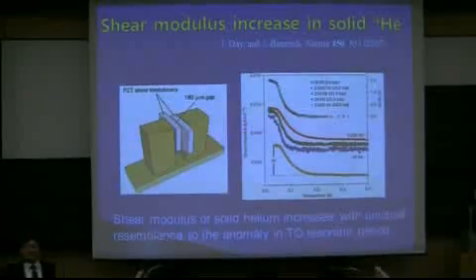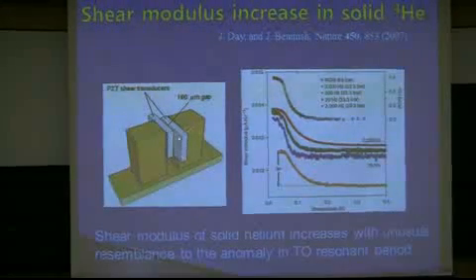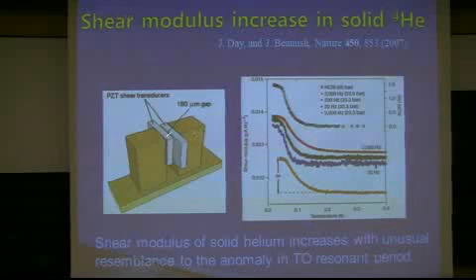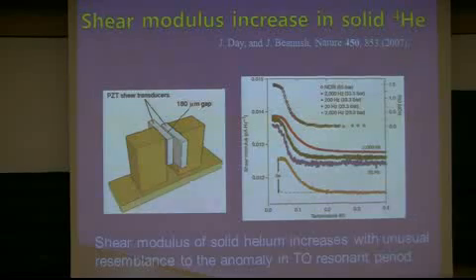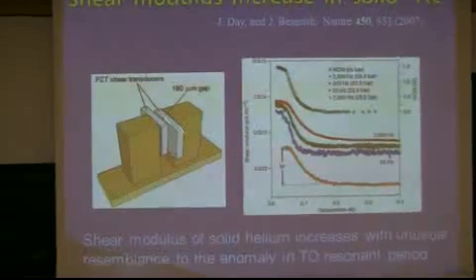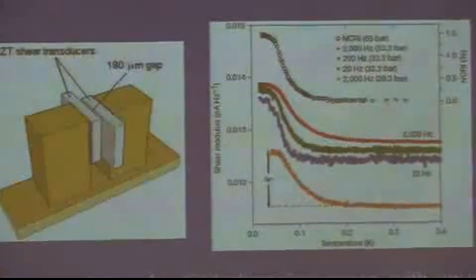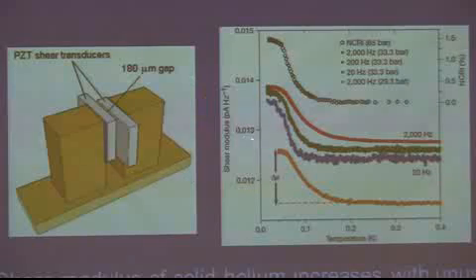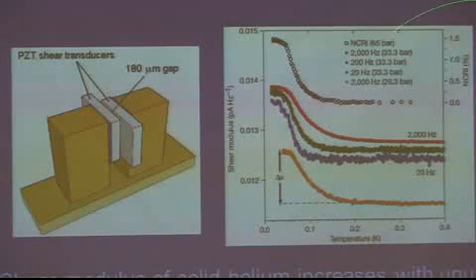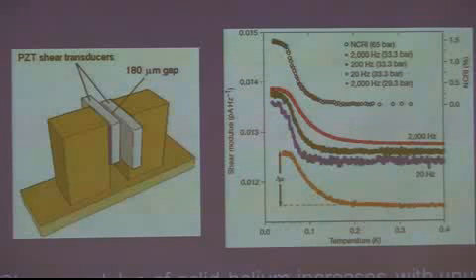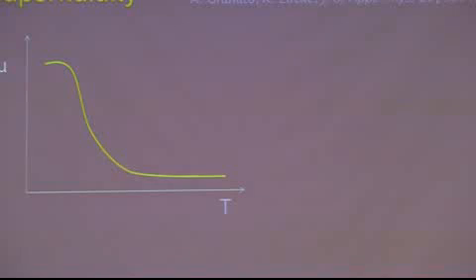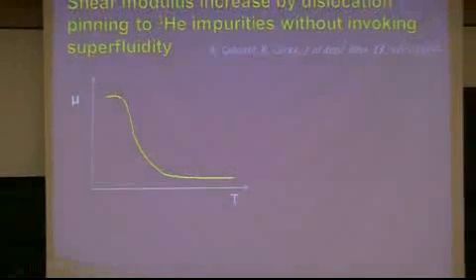Quite dramatically, this kind of elastic modulus change is observed in solid helium. They measured the shear modulus of solid helium by applying strain on one side. In between there is about a 200 micrometer gap of solid helium. If you apply the strain on one side and measure the stress built up on the other side by measuring the current, then you can measure the shear modulus. When they measured the shear modulus as a function of temperature, they found an increase in the shear modulus as well. So it looks very simple, since we can explain the anomalous reduction in the resonant period with just the simple classical idea of shear modulus stiffening, without invoking superfluidity.